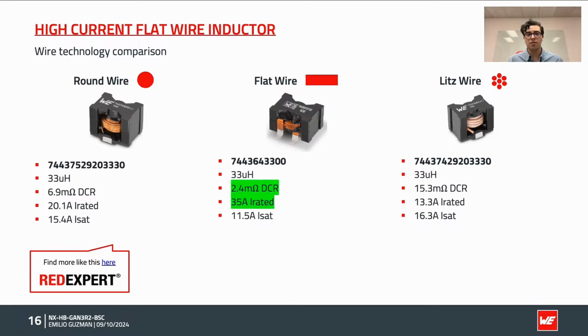And if we took these three wire technologies and picked the same part across the three, we could see the following comparison. These three parts are 33 microhenries and the same core size, but we can see an interesting difference where the round wire has a middle ground DCR. It has a 20 amps rated current, which is already higher than the litz wire, and it has a higher saturation current, a bit higher than the flat wire. Although here the flat wire has the least amount of DCR and the highest rated current.